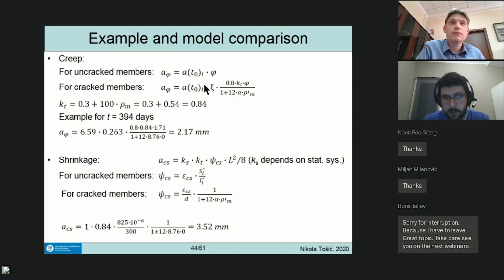In this case, it's this C coefficient, 0.8 times KT, which depends on the reinforcement ratio, that average value, 0.3 plus 100 times rho, times the creep coefficient, over 1 plus 12 times alpha, the modulus ratio, times rho prime, the compressed reinforcement coefficient. Again, the effective average value, which we don't have, so it's 0. What we get is, in our case, 2.17 millimeters, the effect from creep.